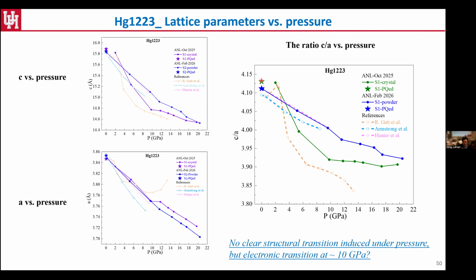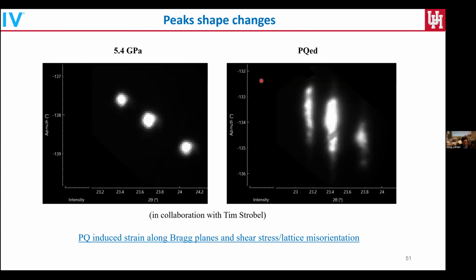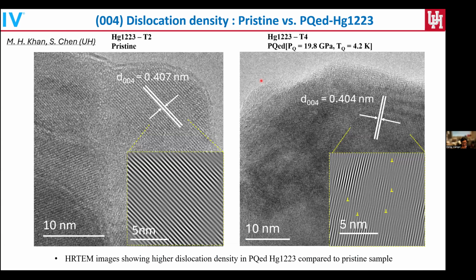So then we looked at even more minor or subtle things, like whether there are defects, or whether the domain size changed. One very positive phenomenon we saw when we looked at the shapes of the X-ray peaks is that they are elongated along the azimuth direction. That's an indication of strain, and also possibly the domains being broken into smaller pieces, right? That's one of the hypotheses here. Another thing, done by Dr. Chen and his student here at UH, was seeing some dislocations through TEM imaging. Again, it's a very challenging experiment.